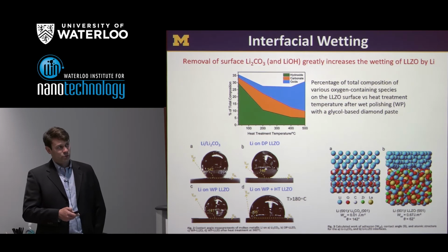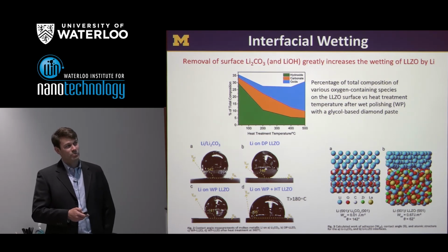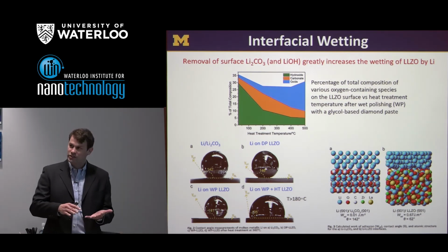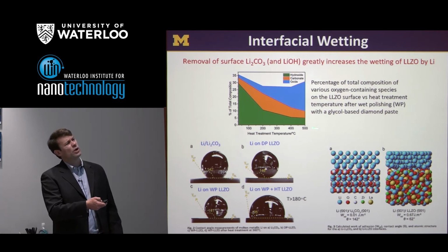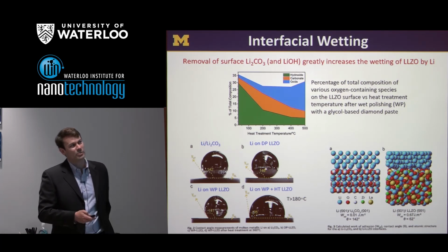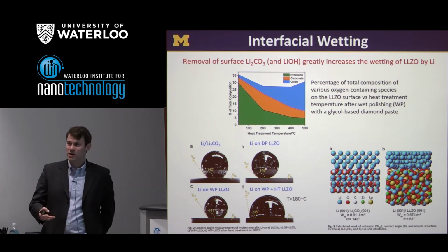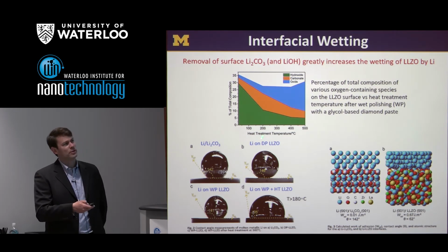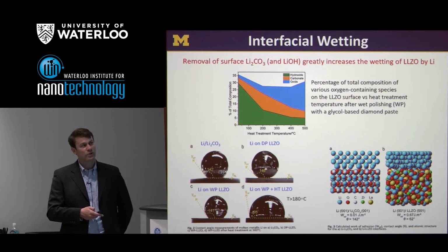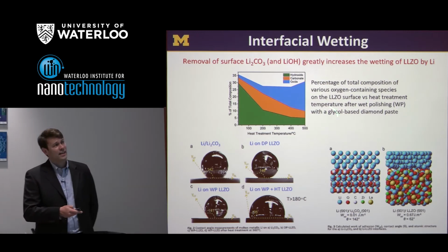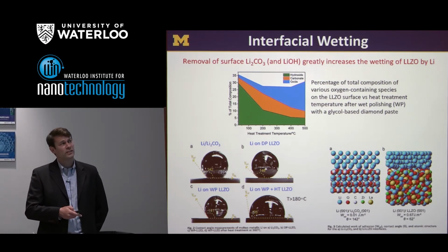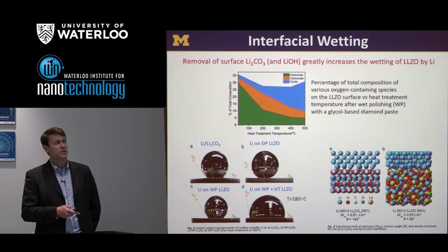And what one of Jeff's students, Asma, has done is look at different polishing strategies, either dry polishing or wet polishing. The wet polishing uses a glycol-based diamond paste. After those polishing steps, they can also optionally heat treat the sample. What they found the best procedure is to go through this wet polishing technique and then heat the system up to about 400 to 500 degrees C. In that case, most but not all of the hydroxide and carbonate disappear.